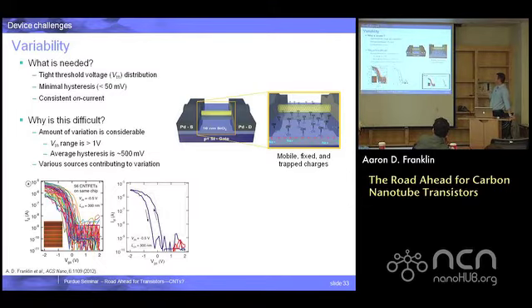Over here is a sort of a schematic picture looking at why this is the case. Nanotubes are these tiny single molecules. So with all that's happening on their surface, nothing is protected. And because of that, they have a lot of sensitivity to what's going on around them. And that makes them great for sensors. They'll pretty much change their conductance in the presence of almost anything. But it makes a problem when I have a transistor that needs to stay the same and be the same as its neighbors. So there's a hydroxylated charge-ended surface, which is on most of these oxides, different traps and charges that are likely part of the dielectric structure, and all of these are going to have some contribution.